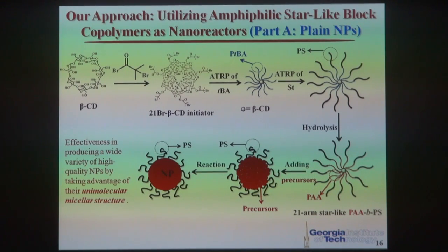So here I already showed you how we make these star-like polyacrylic acid-polystyrene, right? So realize that the inner PAA block in red is highly hydrophilic, so it imparts the preferential interaction of the metal moiety of the precursor you later add into the system with the carboxylic acid groups of the PAA block. So through that particular coordination interaction, you convert your precursor into the nanoparticles by reflux reaction.